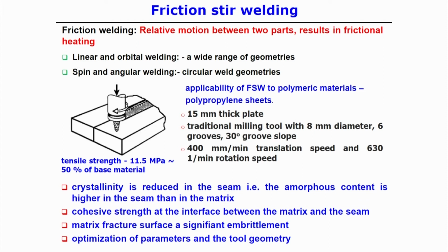So, 15 millimeter thick plates were tried, simply by converting a traditional milling tool, with 8 millimeter diameter, 6 grooves and a 30-degree groove slope. So, here we can use the tool, which is a kind of threaded tool. That threaded tool is used for polymeric materials under the friction stir welding process. Here the translation speed was 400 millimeter per minute and the rotational speed was 630.